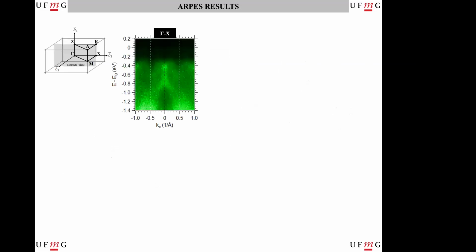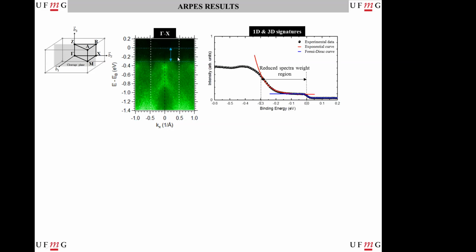So for our ARPES results, we did ARPES with synchrotron light. Here we have an example of an ARPES image taken along this crystallographic reciprocal direction, gamma X, and we saw what looks like a band gap. But when we look closer, we can see the region of reduced spectral weight. We have the Fermi edge cutoff and we have the exponential decay. But in our experiments, we tried to look at directions different from the main directions, gamma X and gamma Z.